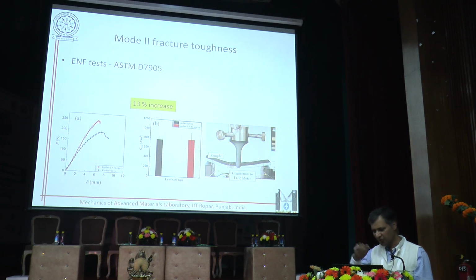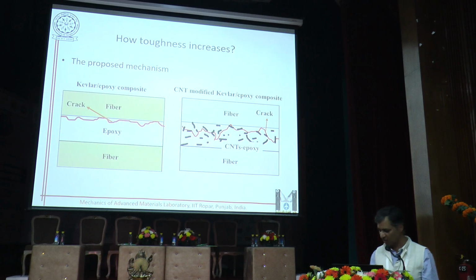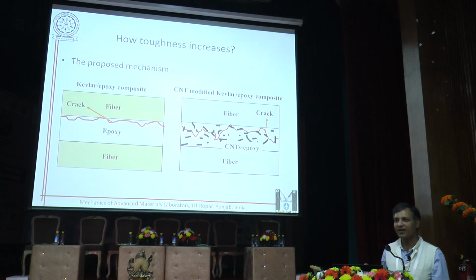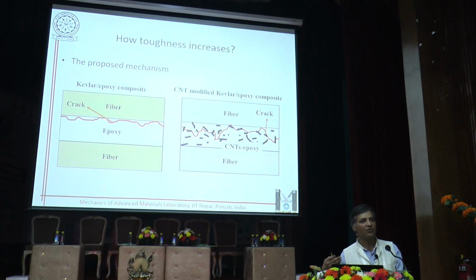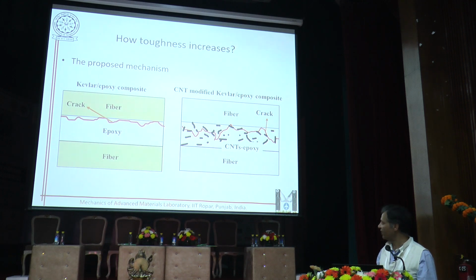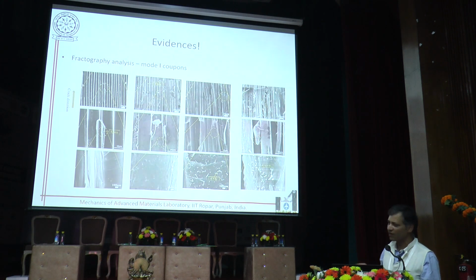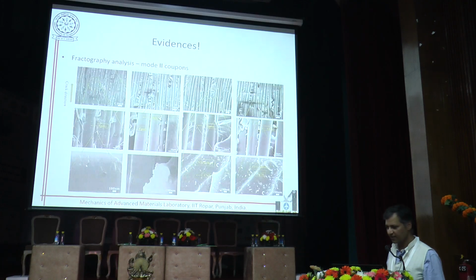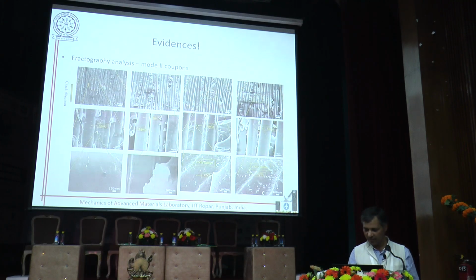And then we looked at the fractography analysis and did some more FEM calculations to come up with a mechanism that leads to this enhancement in mechanical properties. If you look at the conventional system, the crack is growing at the interface, a little bit in the epoxy region. But if you look at the modified system, there is a lot of zigzagging of the crack, and that requires a lot more energy, which eventually leads to higher toughness of this modified system, right? So we have good evidence to support this mechanism. In the fractography analysis, looking at the pictures more carefully, you see a lot of matrix cracking, and these are CNTs pulling out here, so they take extra energy from the system. We observed the same thing in mode 2 as well. So all these mechanisms lead to higher toughness and higher mechanical properties.